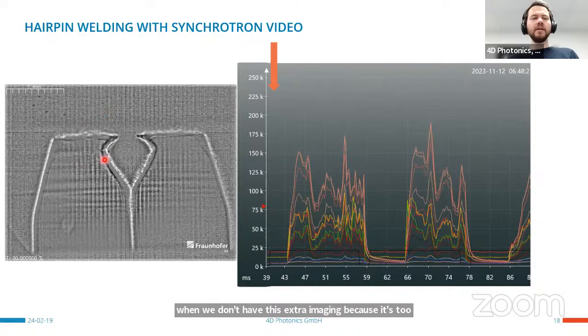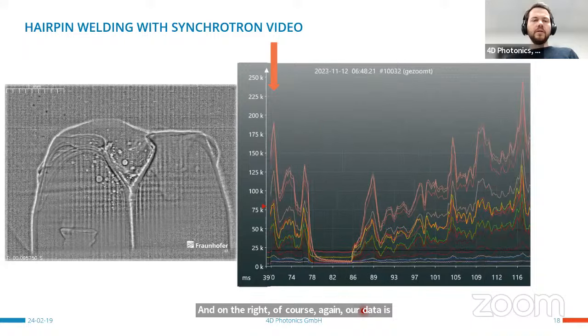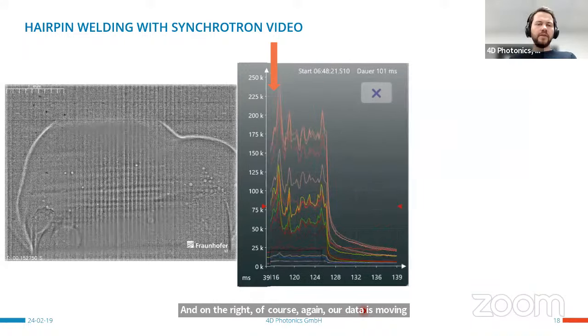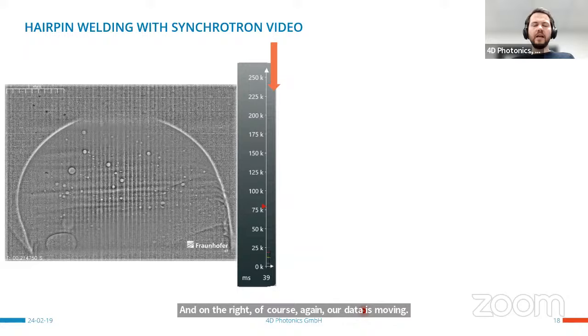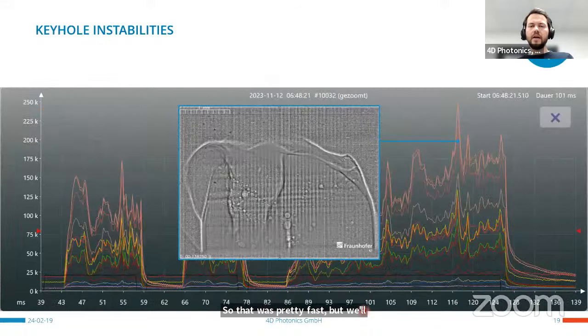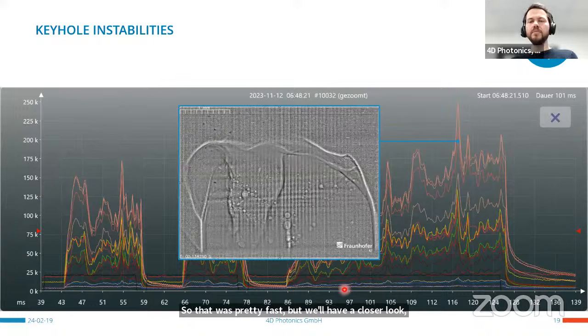We can see again one weld seam on the left, one on the right, and then a combination of them. And on the right, of course, again, our data is moving. So that was pretty fast, but we'll have a closer look right now. So we can see a couple of peaks during this weld seam. That's good for us because it's not really an okay welding. We have a couple of pores at the end, and we can investigate a couple of things during this welding.